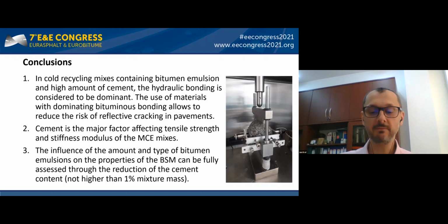Those results came from an early stage of the project. So now I can say that in the next stage of implementation, BSM mixtures based on bitumen emulsion were developed, which met the expectation in terms of lower stiffness and higher flexibility. And a maximum of 1% of cement was used for them only as an active filler. So not a cement binder, but active filler.